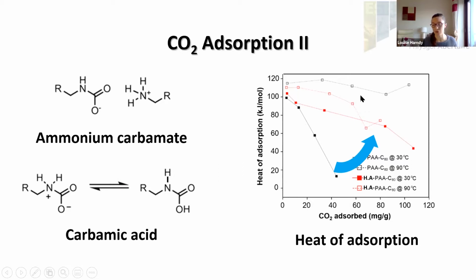At 90 degrees, however, we see that the heat of adsorption is effectively lowered on inclusion of the hydrophobic additive. Now, we know that the hydrophobic additive material has lower amine concentration, and these amines are more likely to be more isolated from one another. So we believe that this material is more likely to form carbamic acid. Now, this only requires one amine per CO2 adsorbed, and this has a lower heat of adsorption, whereas for PAA-C60, which has more amines, it's more likely to form ammonium carbamate, which involves 2 amines per mole of CO2, and this has a higher heat of adsorption.